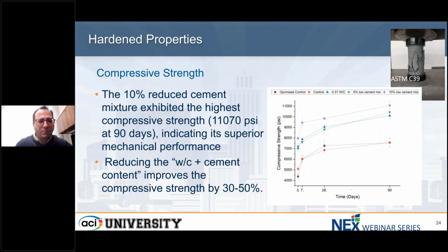So other than the fresh properties, we looked at the hardened properties, starting with the compressive strength. We used ASTM C39. We made 4x8 cylinders and cured them for different times in submerged lime water: early ages, 3 days, 7 days, up to 90 days. So this is the data set you are seeing at the right side. As we expect, when you reduce the water cement ratio, we have to see higher strengths, right? That's what you are seeing here.